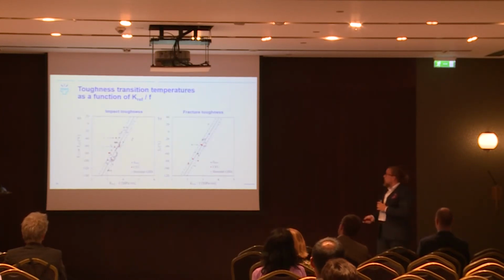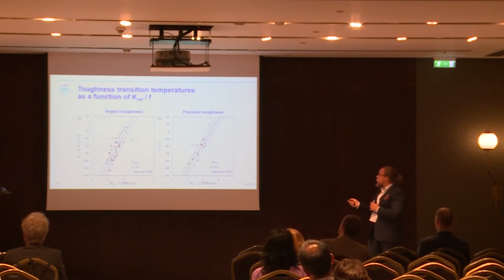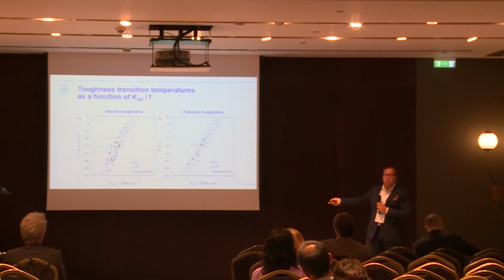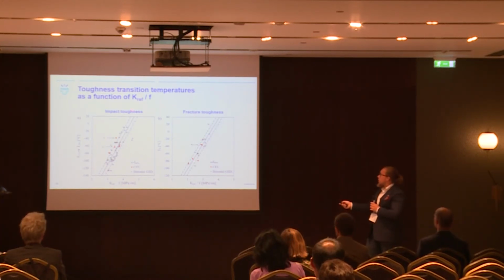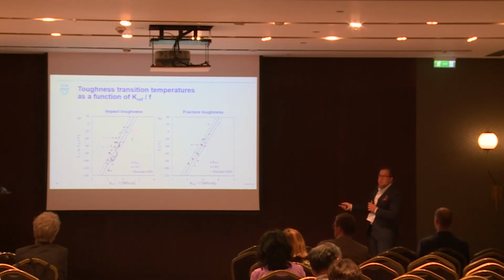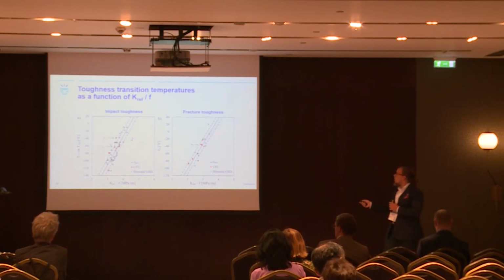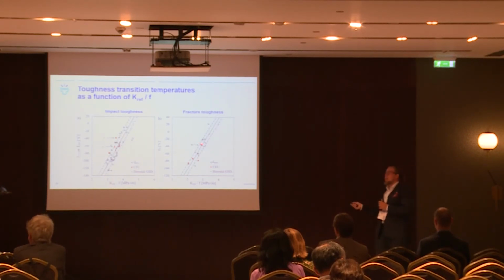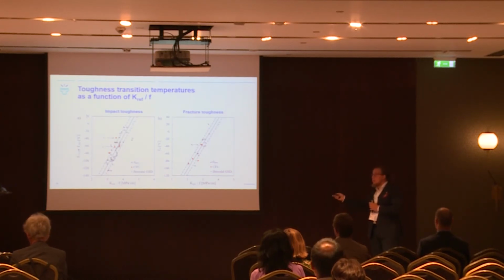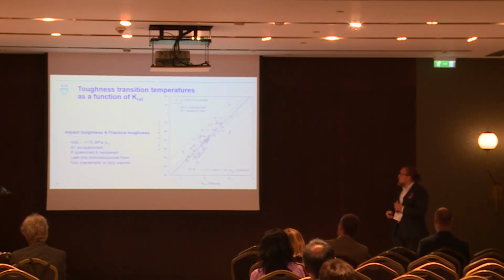So, running mostly out of time, so just showing you very shortly what we can do with this one parameter of the propagation of the local microcrack with the sufficient size. With impact toughness, we get, with roughly almost 50 samples, this nice tight fit, and with fracture toughness tests, we are a bit more limited in our materials, but also get a similar trend with a slightly lower slope. And these are divided by this specimen-dependent and notch acuity-dependent term. And when we use this general ratio between the fracture strength and yield strength, we get this.